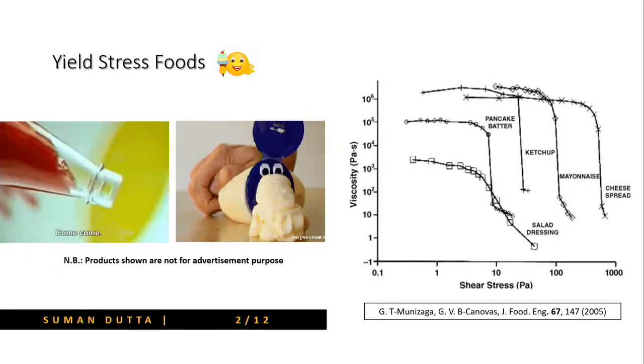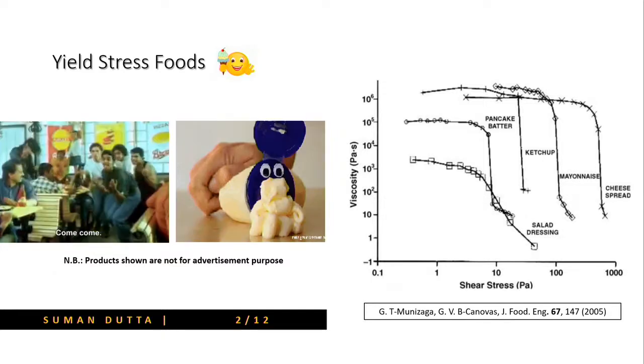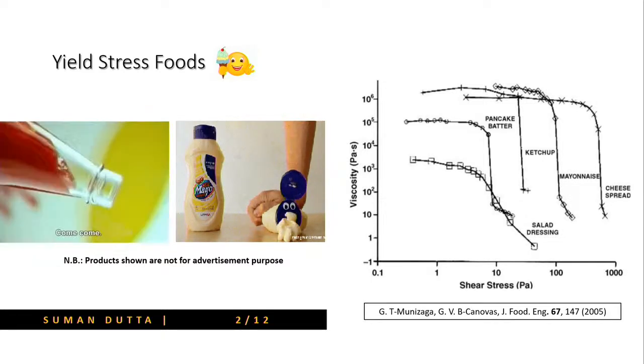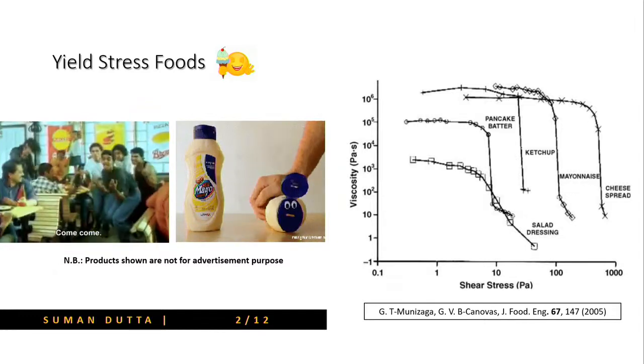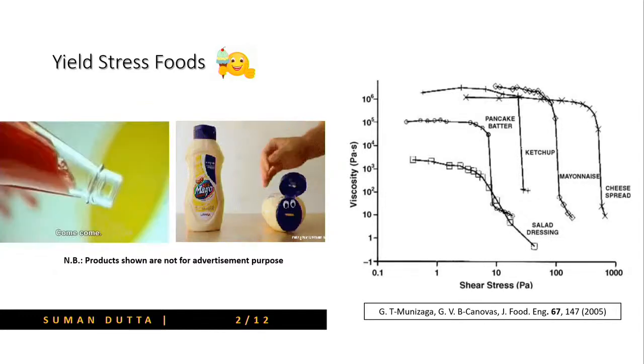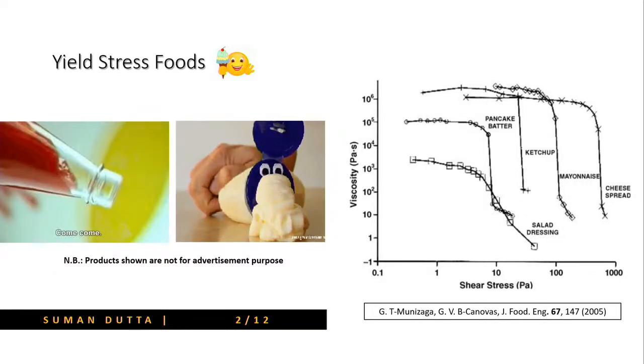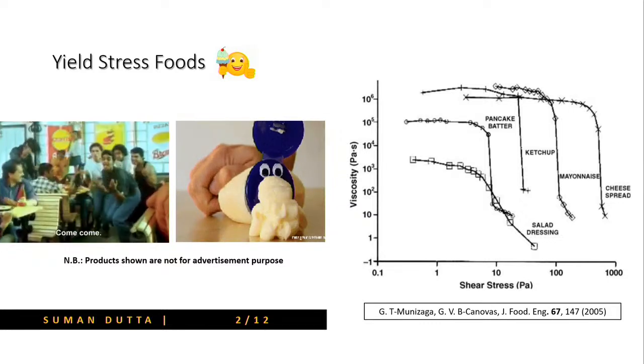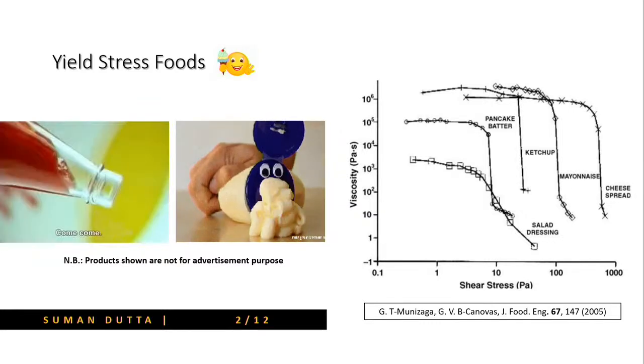Initially they are in a solid-like state, which are viscoelastic solids. Then, as the shear stress on this material is increased, they suddenly fluidize, there is a drop in the viscosity, and they become viscoelastic fluids. So the question is, do we understand this regime, where there is a sharp drop in the viscosity, and how to understand this behavior of yielding?